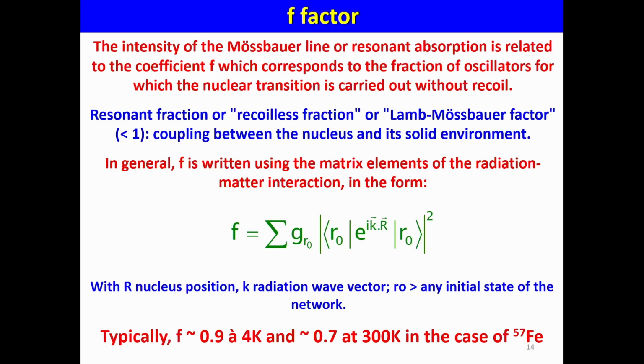I think in the case of tin, it's much more important than in the case of iron. Maybe it's important to say that so far it's a local field. That means if you have two concentrations, then the dynamics and local dynamics can be different. So that means you have a different Lamb-Mossbauer factor. Yeah.